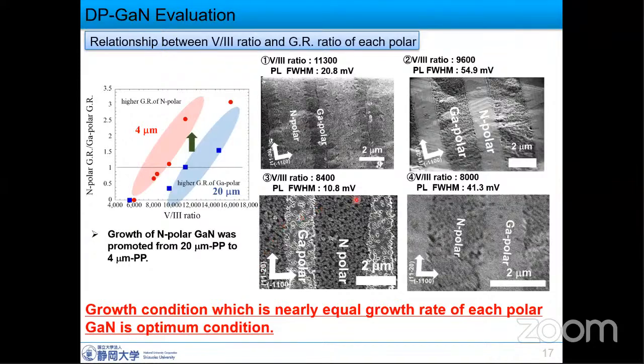So next, I'm talking about DP GaN evaluation. This graph shows the relationship between V/III ratio and each polar gallium nitride growth rate ratio in each pitch pattern. Following the graph, at high V/III ratio, the nitrogen polar gallium nitride growth rate is faster than the gallium polar gallium nitride growth rate. And at low V/III ratio condition, the gallium polar growth rate is faster than the nitrogen polar one. And the nitrogen polar growth rate in the 4 micrometer pitch pattern is faster than in the 20 micrometer pitch pattern.